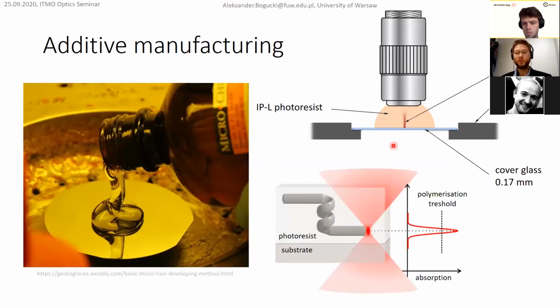And by moving, you can move both things. So you can move, of course, the laser beam, or you can move the substrate, and by that you will obtain this polymerized trace, so this solidified photoresist. And it's only solidified in a small region, when the power of the laser is sufficient, so it's above the threshold of polymerization.